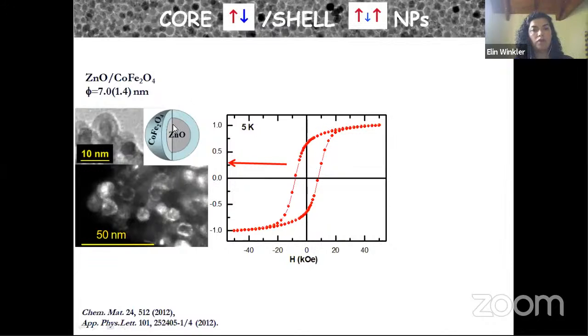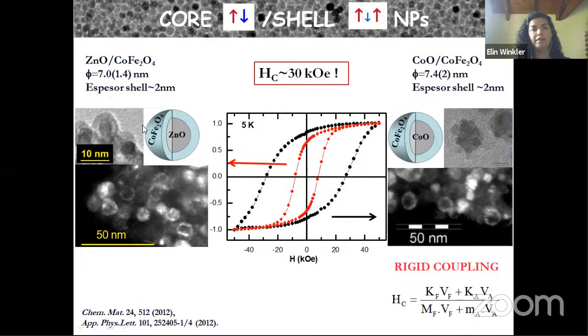This hysteresis cycle corresponds to the zinc oxide encapsulated with the cobalt ferrite. Here, for example, the core shell structure is very clear. Yes, and here the bright corresponds to the shell. And the coercive field is approximately 7 kilo-oersted. When instead the zinc oxide core is replaced by cobalt monoxide, the hysteresis cycle grows more than 3 times. Yes, the coercive field reaches up to 3 Tesla. In this case, what is the difference between these two materials? Well, remember, the cobalt monoxide is an antiferromagnetic material, so the magnetic saturation will remain more or less the same, but this system presents exchange coupling at the interface, so the coercive field will be an average of the properties of both phases.